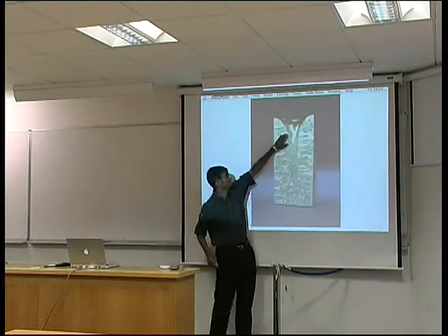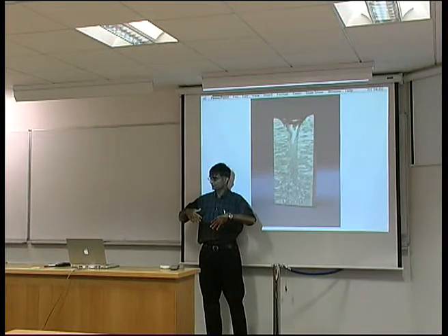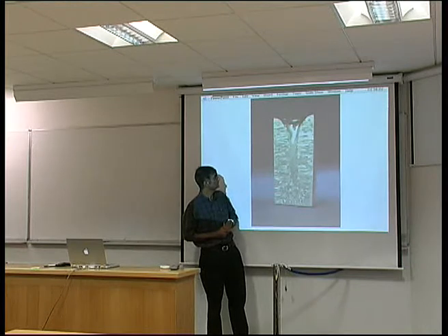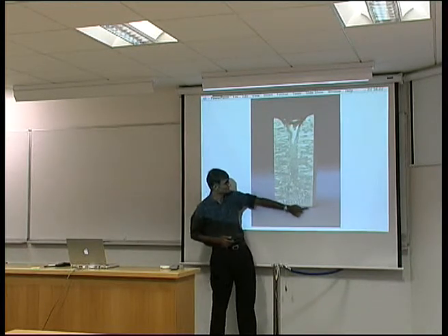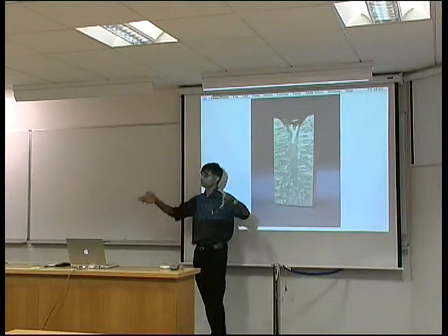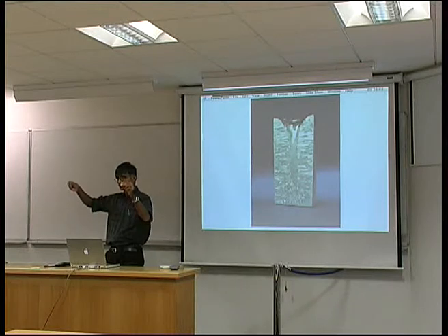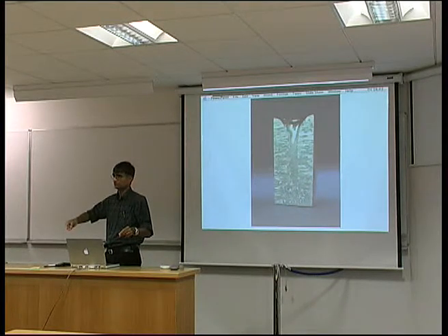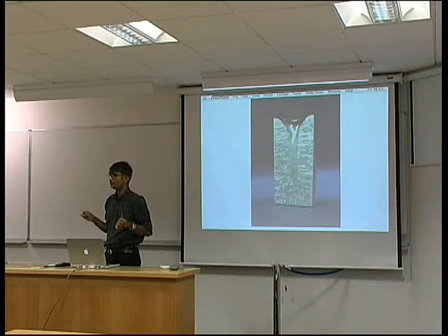And the stuff that you see in the middle is a big hole because of the shrinkage of the liquid as it solidifies. But what I'd like you to notice is that right at the edge, there are some very, very fine crystals. Okay? Because as you pour the molten metal into the mold, you get very quick freezing at the surfaces of the mold. And that stimulates a lot of crystals to nucleate.